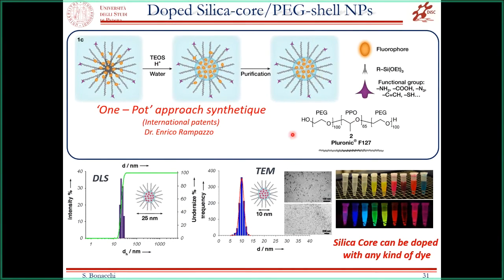Basically, we took advantage of this block copolymer, the Pluronic polymer, to create a sort of micelle in a water solution, and this micelle acts like a template to synthesize the silica core, in which it is possible to trap different kinds of dyes. So we can spontaneously trap different kinds of dye if they are more hydrophobic, or we can easily modify the dyes with triethoxysilane derivatization to really anchor them inside the silica core. And then by using a very easy purification approach like ultrafiltration, dialysis or centrifugation, we can purify the